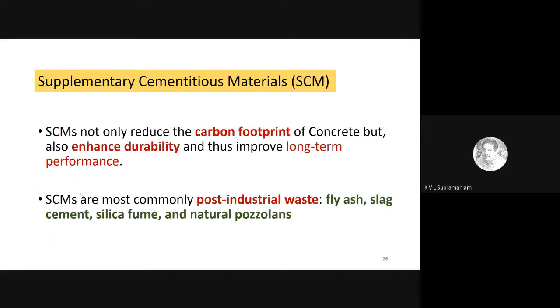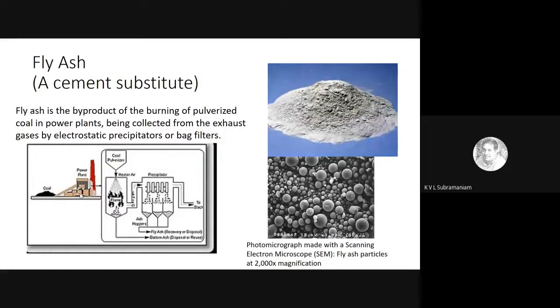Now, we need to understand that because we are trying to reduce our requirement of cement, we started exploring supplementary cementitious materials, which are primarily derived from post-industrial waste. The supplementary cementitious materials most commonly used today are fly ash, slag, and of course silica fume, and these are all waste materials. Now, what is fly ash itself? I'll cover this in a little more detail in the next few slides. It's basically what we get when we burn coal, the ash that is left behind. This is the ash that is collected from the stack, what is coming out of the chimney. It's carried by the flue gas, it's in the form of fine dust, and it's collected using electrostatic precipitators.